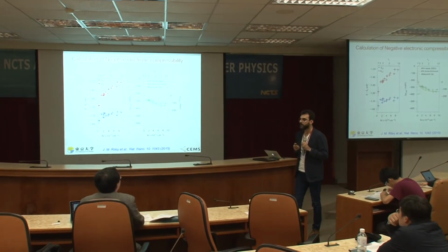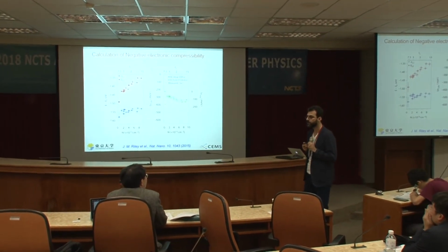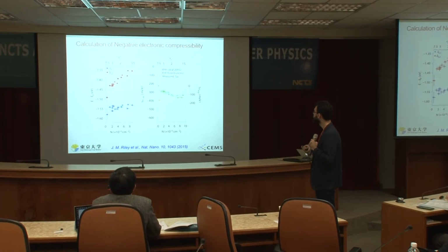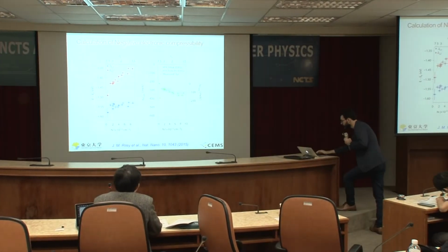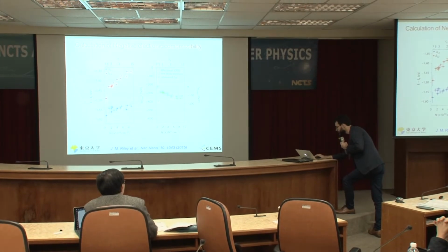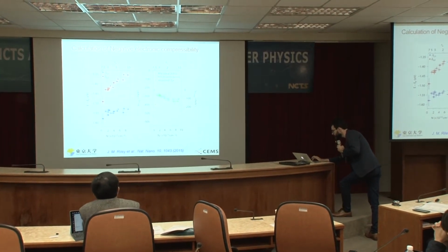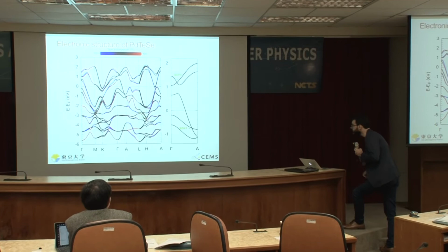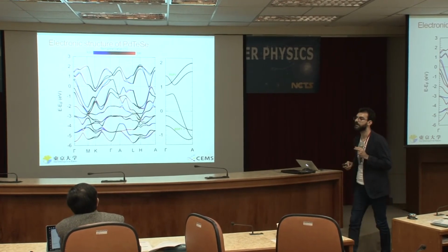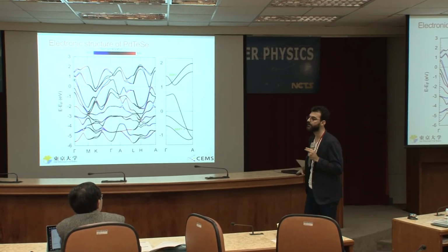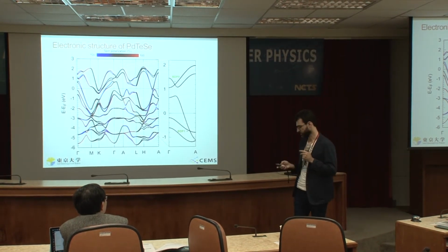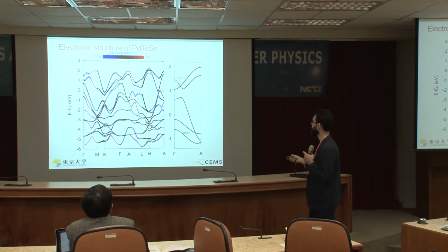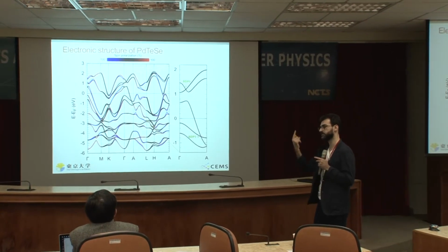Concerning this palladium telluride selenide, you said that even though you break spatial inversion symmetry, you still have a Dirac point. But I would guess, even at the beginning, this Dirac point is not due to inversion symmetry, but maybe due to some mirror symmetry or threefold rotation symmetry. So this protection, you see that happens along gamma, where we have this rotational axis.